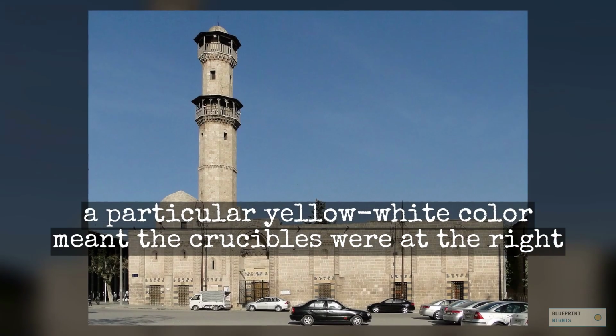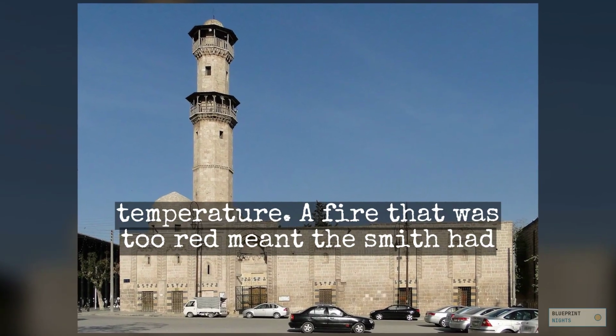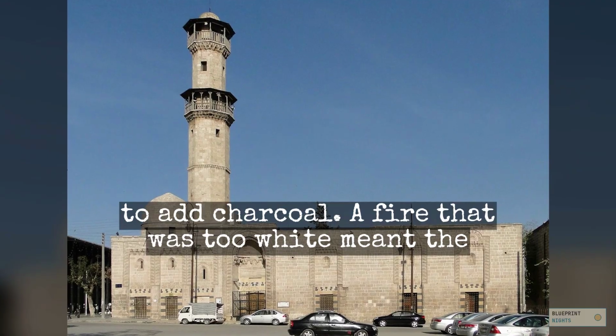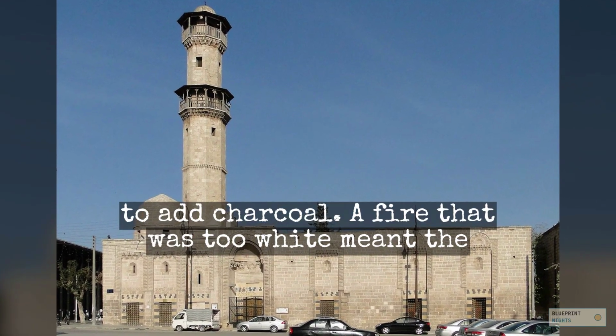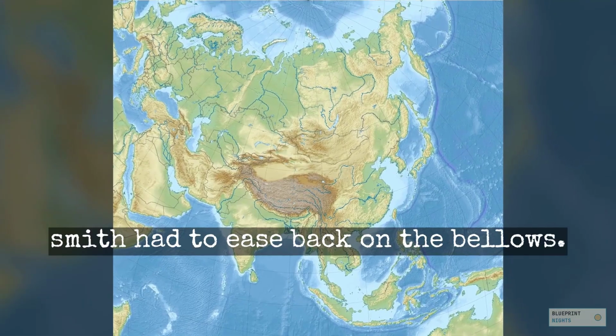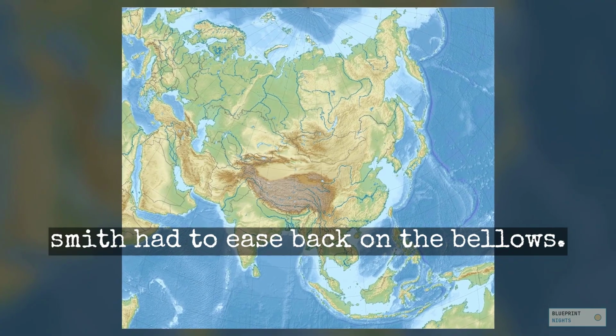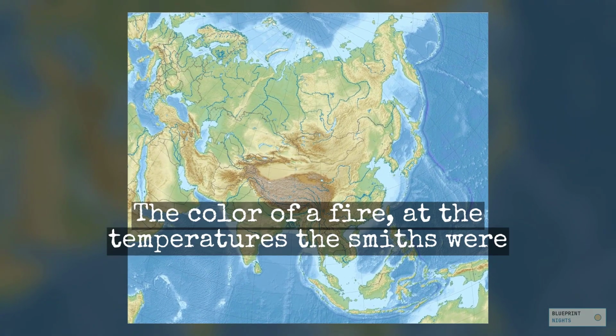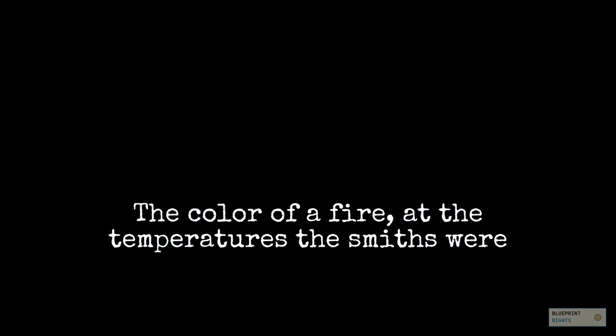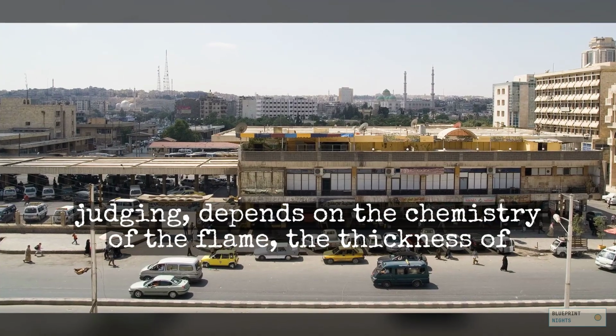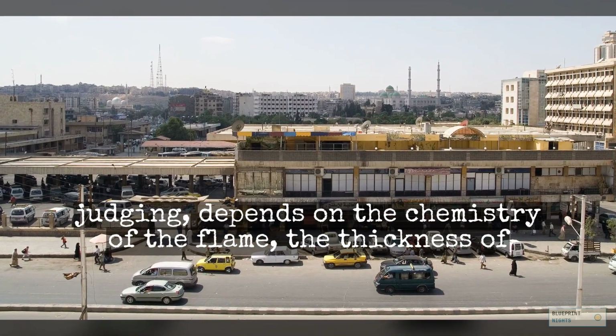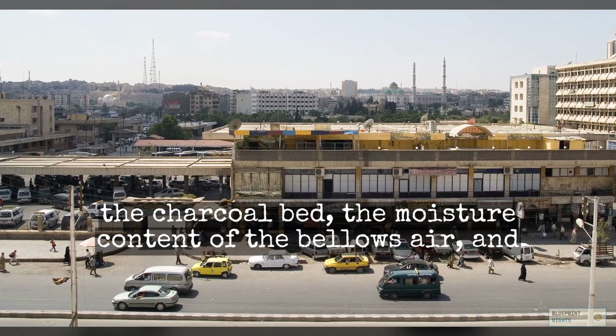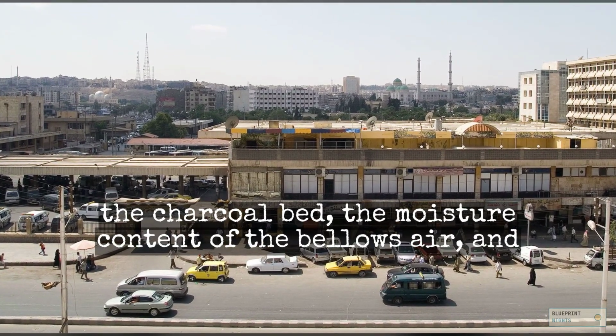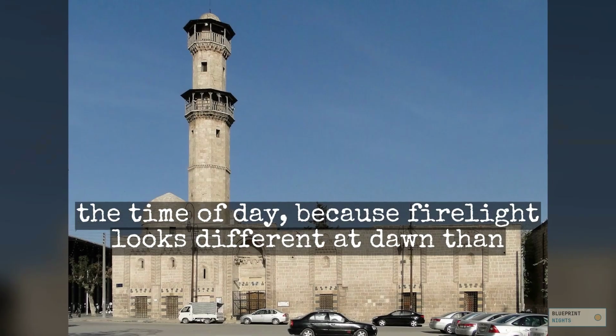A fire of a particularly yellow-white color meant the crucibles were at the right temperature. A fire that was too red meant the smith had to add charcoal. A fire that was too white meant the smith had to ease back on the bellows. The color of a fire at the temperatures the smiths were judging depends on the chemistry of the flame, the thickness of the charcoal bed, the moisture content of the bellows air, and the time of day, because firelight looks different at dawn than at noon.